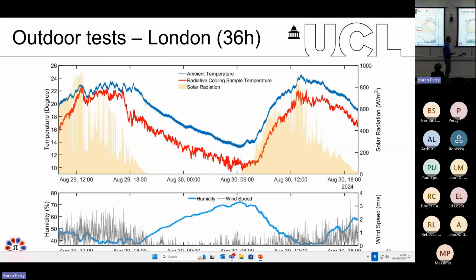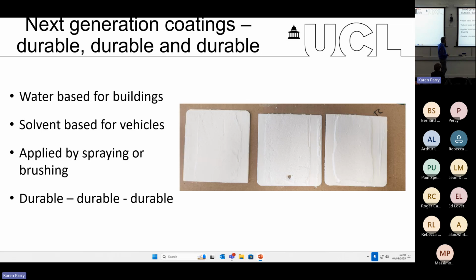And we actually measured the temperature with a thermocouple on our sample against the ambient temperature, the blue line, whereas the temperature on our sample is the red line. And this is the first demonstration of radiative cooling on UK soil. For 36 continuous hours, we got cooling of about 4 to 5 degrees. There's a very nice correlation between the amount of cooling and the solar radiation, which basically indicates cloud coverage. And the main enemy to radiative cooling is moisture, is water, and is cloud cover. It's a renewable resource in the same way that, if the wind doesn't blow, you do not generate electricity. In the same way, when the clouds are out, you don't get much radiative cooling.